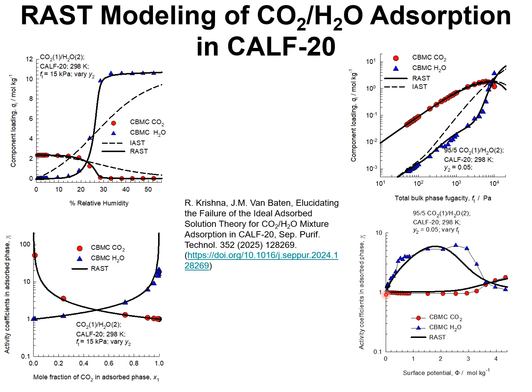In other words, the activity coefficient models should not only respect the limiting values for the activity coefficients at either end of the adsorbed phase mixture compositions, but also they should respect the fact that at low pore occupancies in the Henry regime, both activity coefficients should tend to unity.